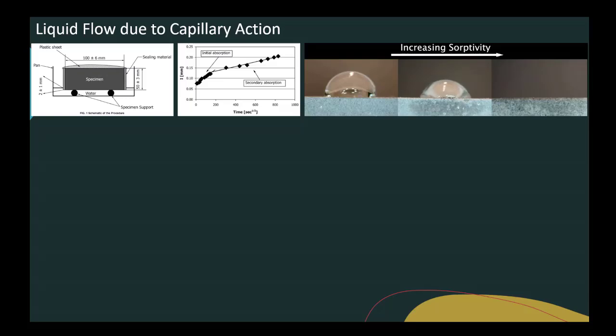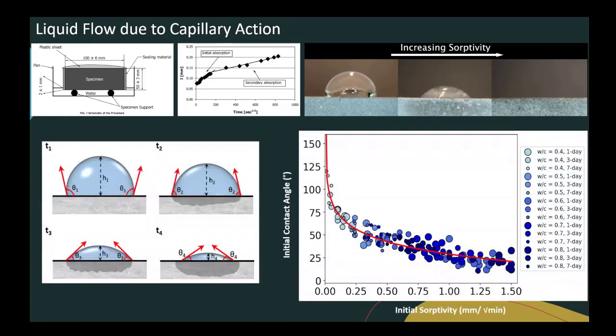What I can capture is the initial absorption rate. What I cannot is the secondary absorption rate. And the secondary absorption rate is due to the slow dissolution of entrapped air in the sample, while the initial is the initial capillary suction. So this droplet method can only predict the first one. So this shows I was able to predict the initial sorption in a matter of seconds, but I couldn't do the second one. Then how to do the second one?